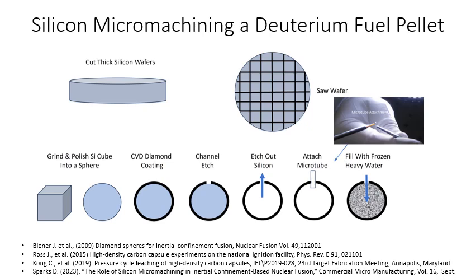Now here's the rest of the steps for making these fuel pellets. Again, start with a thick silicon wafer, dice it into cubes, round off the corners, polish a sphere. You then coat that sphere with a diamond shell. You've got to etch a single tiny channel into that diamond shell. The reason you do that is shown next, because next you have to etch out the silicon. You've got to remove the silicon and leave behind a hollow diamond sphere.